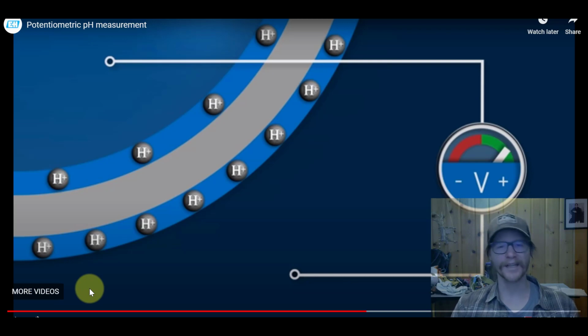And by measurable potential difference, what is literally meant by this is in that modified version of the Nernst equation, which I showed you in the previous video, where you have a constant plus the 59 millivolts over n log activity. This is log activity of protons now. So every time the proton concentration changes by a factor of 10, an order of magnitude, we would measure a 59 millivolt change, because n equals 1. This is proton. So what that literally means is that for the pH, which is a log term, every 1 pH unit that changes, we get 59 millivolts change.